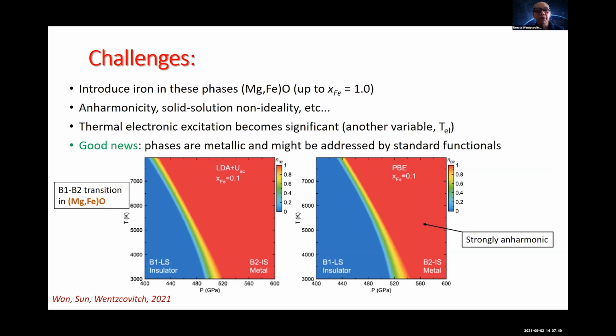Anharmonicity is a really big problem here. At low temperatures, the site distorts, doesn't want to remain cubic. The iron site is not cubic, it is distorted. Unstable phonons, and there is another complication here as well that can save the day for us. Essentially, these are metals. These phases with iron are expected to be metals at the pressures that we want to study them, which means thermoelectronic excitation is going to be significant. To a certain degree, it saves the day because thermoelectronic excitation stabilizes phonons.